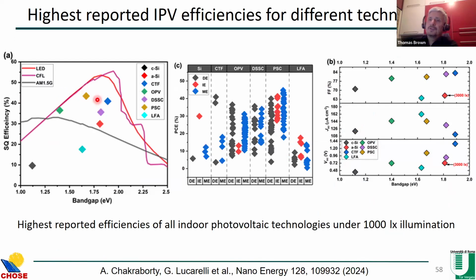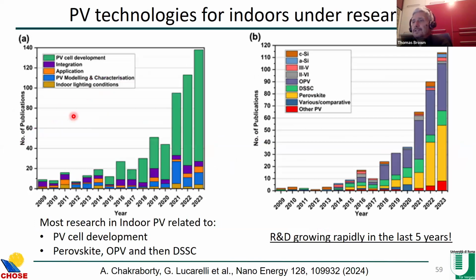Now there are reports of above 40%, which is the highest reported for any technology. Compound semiconductors are also above 40%. DSSCs and OPV are above 35%. So these emerging PV technologies have a lot of potential for entering the photovoltaics market for indoors, because the efficiency is much greater than what is now the dominating technology, which is silicon, and could be an entry point, an entry market for these technologies until they're ready to compete with silicon for high volume markets outdoors.